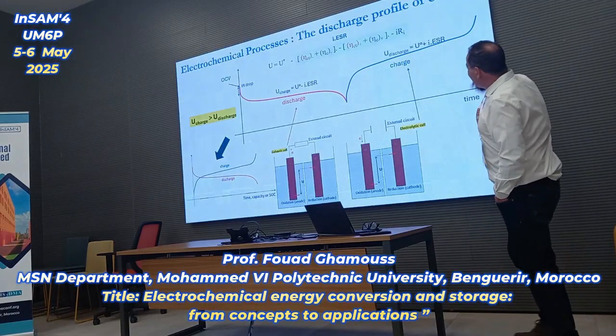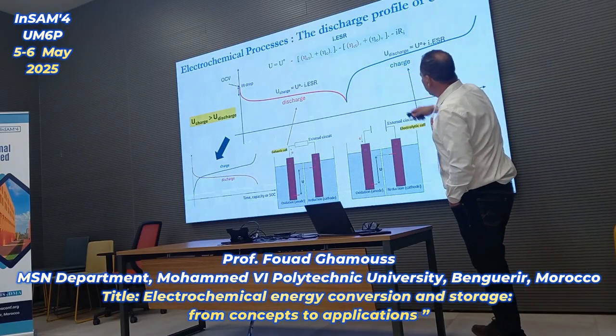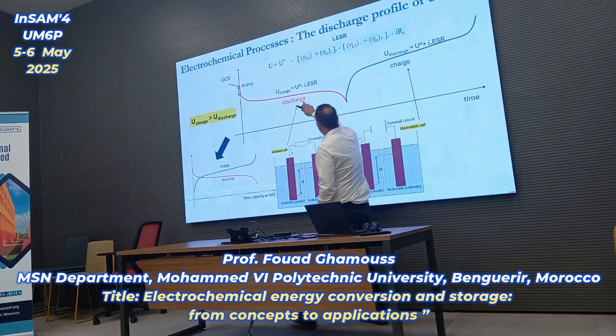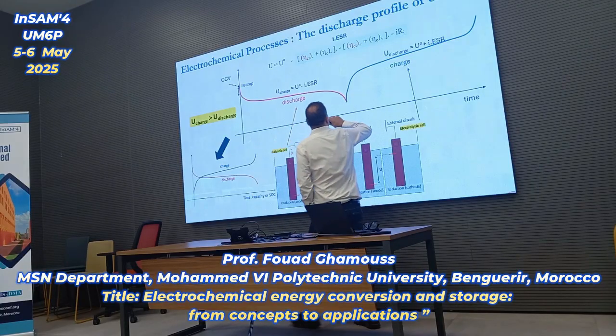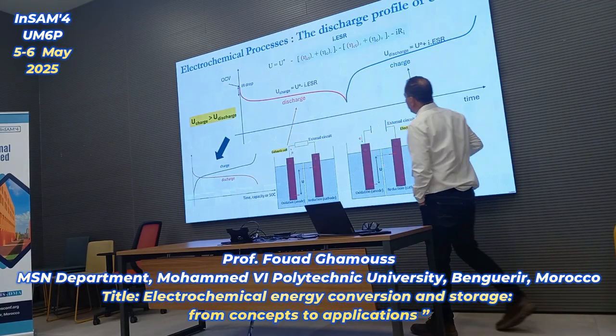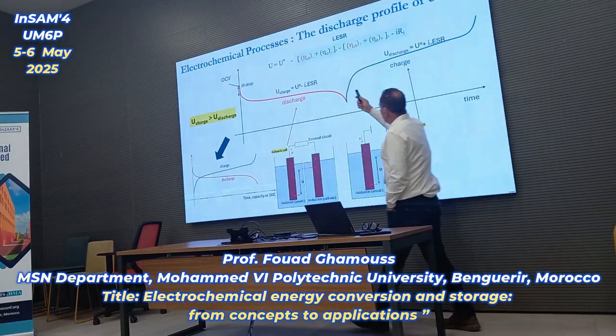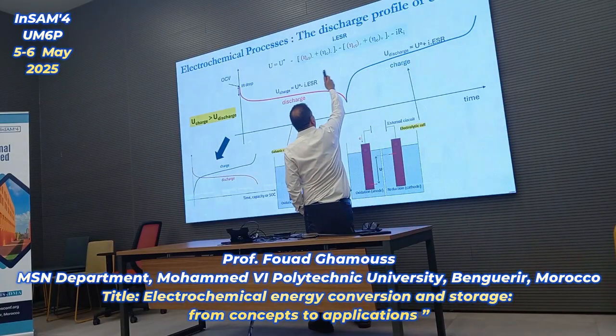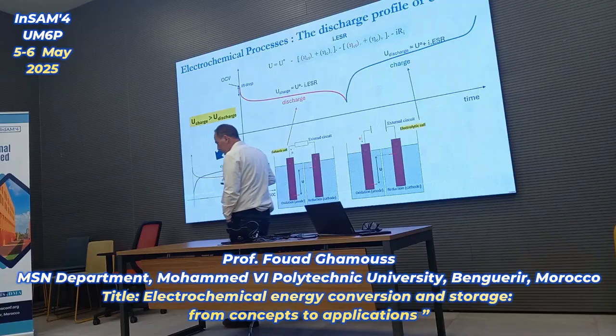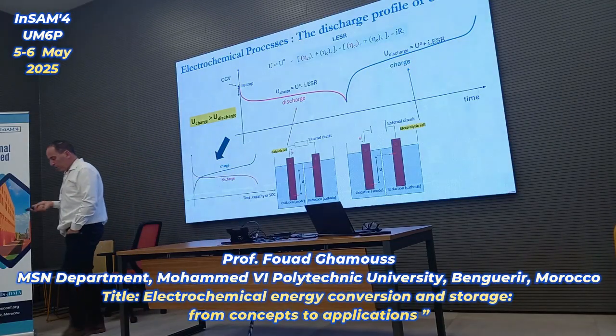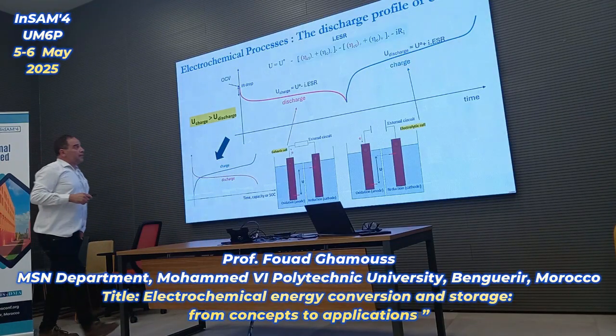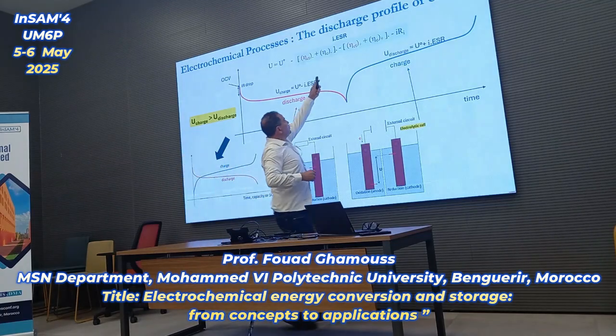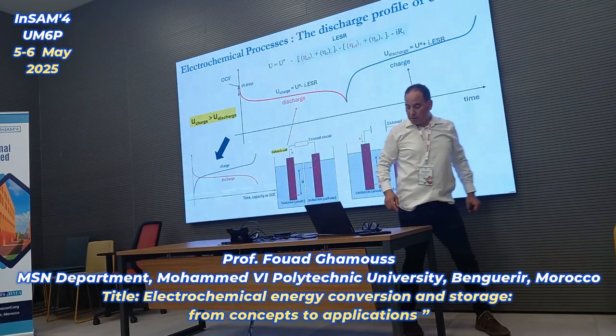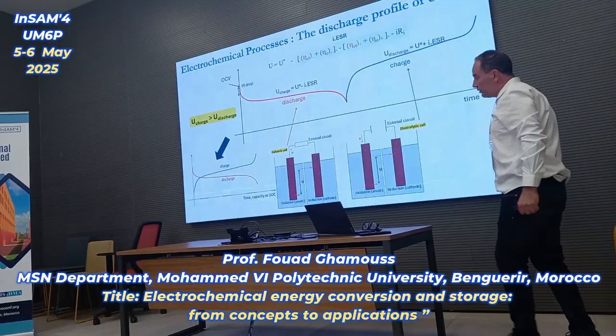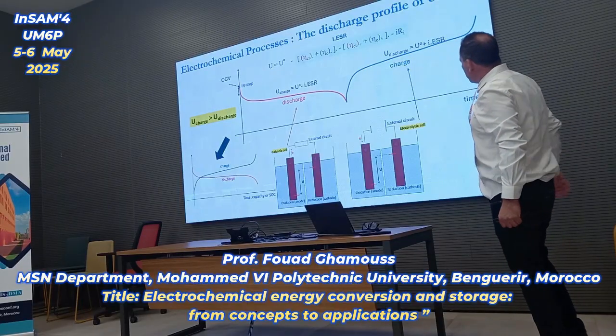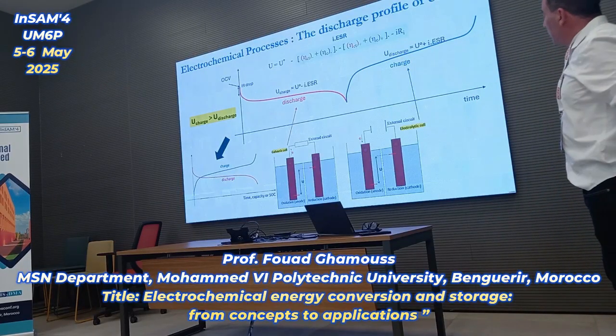So this is the charge and discharge, and this is the detailed equation that gives the voltage, here in the plateau, and here in the plateau at the charge. Those terms are the overpotential due to the charge transfer reaction at the cathode and the anode, and those ones are related to mass transport at the anode and the cathode. And the resistance mainly comes from the electrolyte.